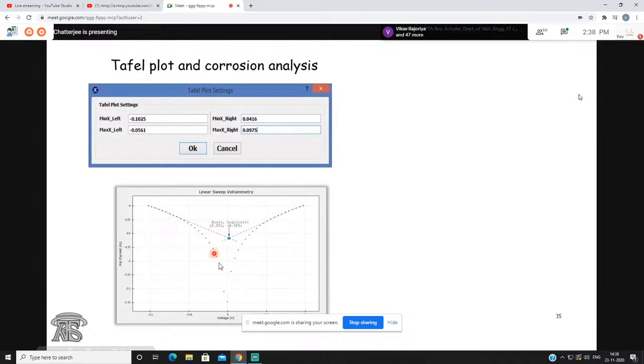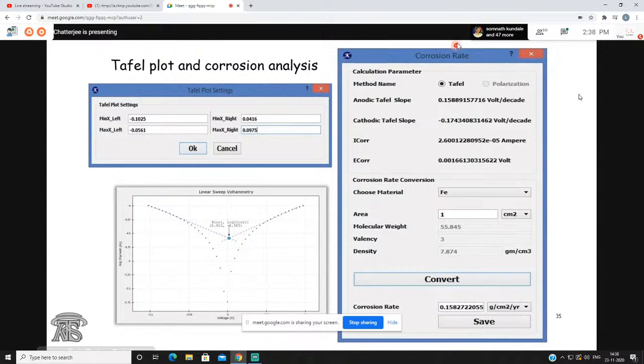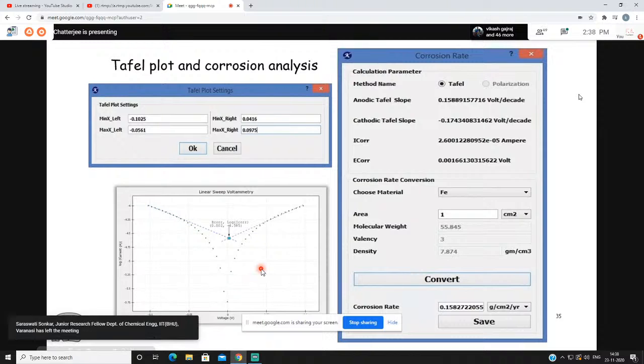So this is actually the plot that we get. This is the voltage versus log I plot. This is a Tafel plot. In our software we choose two different values from the linear portion, and we get the intersection of these two slopes, and we get the E corr value. This is the E corr and I corr, and then we calculate the corrosion rate, because now we have the anodic Tafel slope and cathodic Tafel slope, and from that we can calculate the corrosion rate using the formula of the corrosion.